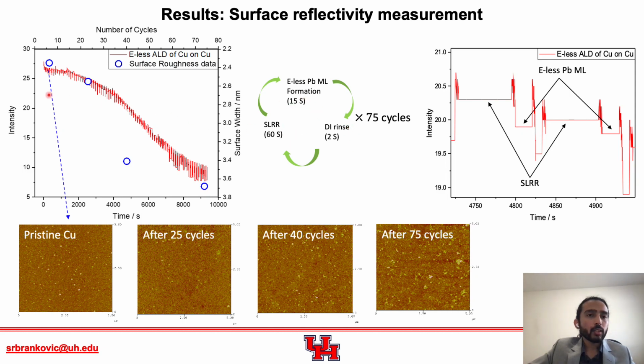An overall reflectivity trend for this 75 cycle is shown here in this graph on the left side of the screen. So we can notice from the graph that surface reflectivity is decreasing from starting to end of 75 cycles. And these images are AFM images for the same substrate at different intervals. And we can notice that from pristine copper to 75th cycle, we see surface being rough due to this electroless deposition cycles. And the roughness is shown here on the right side of the graph with these blue circles.